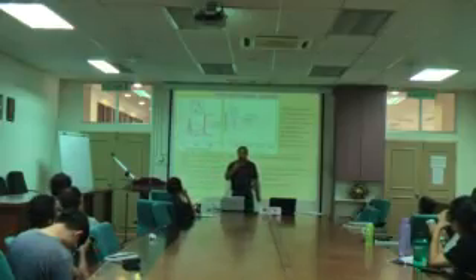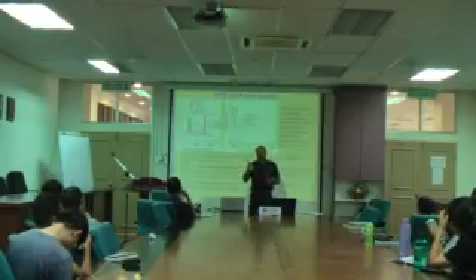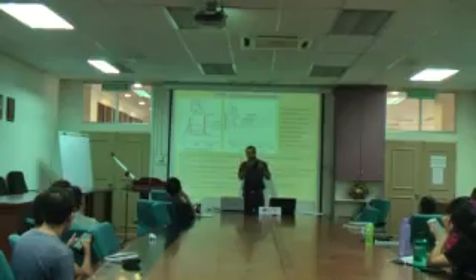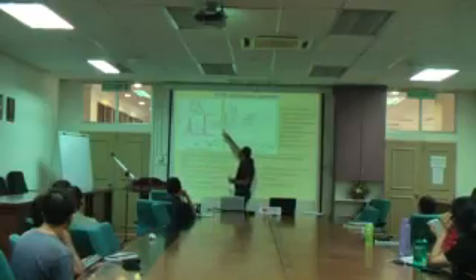So the shift in the Raman spectra is a competition of 2 things: strain and confinement effect. The confinement effect tries to shift to the lower frequency. Strain tries to shift to the higher frequency. So finally, they fight with each other, and it finally shifted to the higher frequency. But not too much, only 1 inverse centimeter.